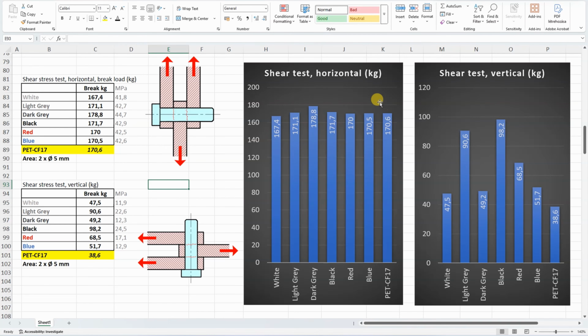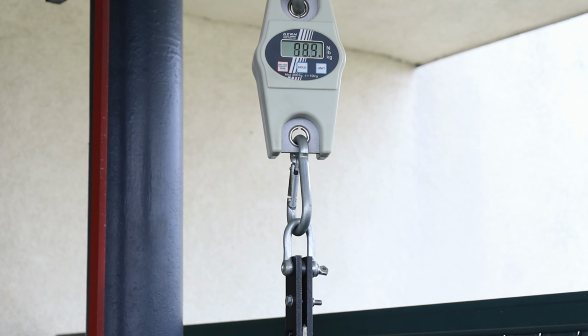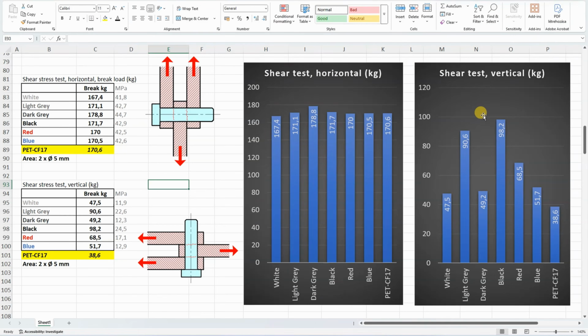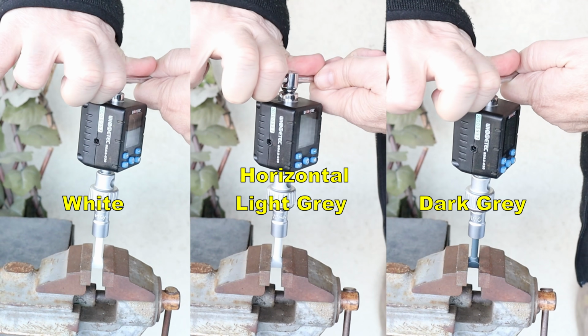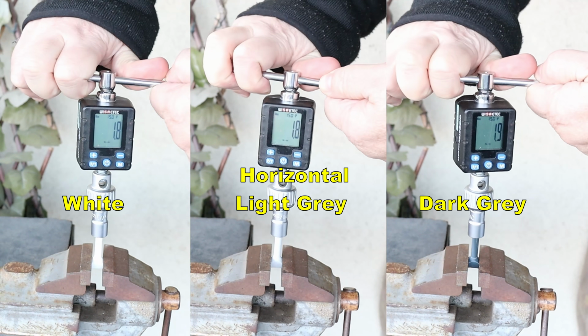In horizontal position, very constant results and very similar to the carbon fiber version. Now, printed in vertical position, I already mentioned that I had the feeling that somehow it broke and then rotated and stuck in the hole, so that's why we have these huge jumps. But I think around 50 kilograms is a more realistic value, and even then it is stronger compared to the carbon fiber version.